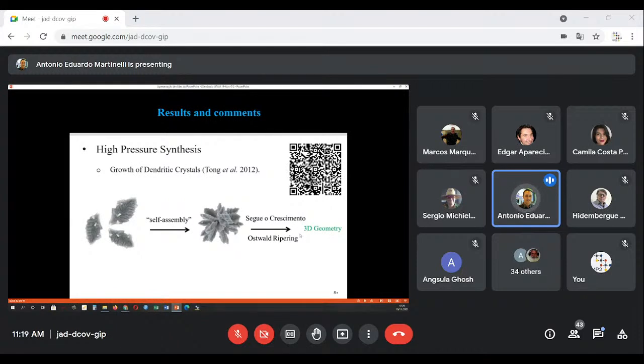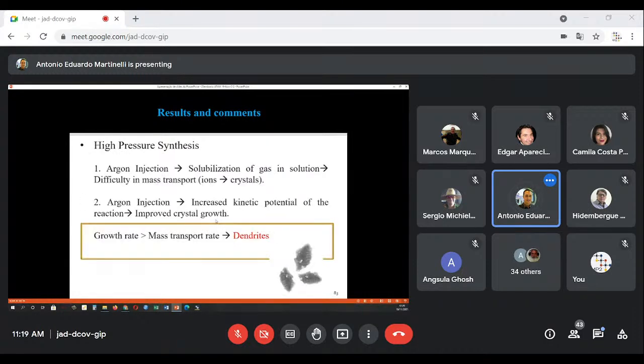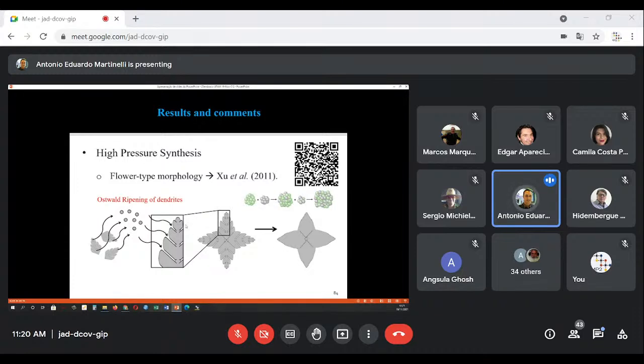Also, another work by Tong, 2012, showed the self-assembly by Ostwald ripening, resulting in the 3D geometry of flower type particles. So the injection of argon, inducing the increase in pressure, worked with the solubilization of the gas in solution, and this increases the difficulty in mass transportation from ions to crystal, and increases the kinetic potential of the reaction, improving crystal growth, which drives the formation of dendrites. So again, here is the flower type morphology.